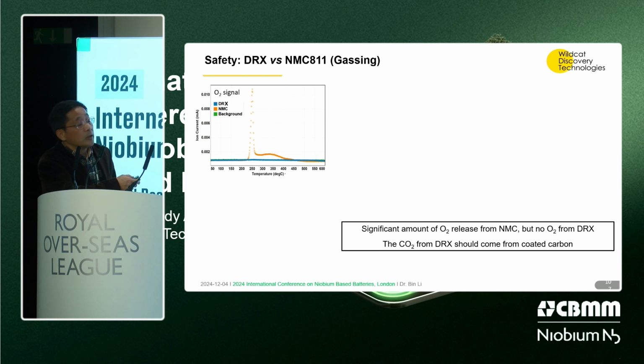One more slide is for the oxygen release. For the high nickel ones, one of the dangerous things is oxygen release. When you have cells with good sealing, in order to catch fire, you need oxygen. You need a fuel, which you have. Here we're showing that when we heat up those cathode materials, for the DRX, we do not see any oxygen released, even up to 600. But for the NMC, you do see the oxygen release at around 220 degrees C.